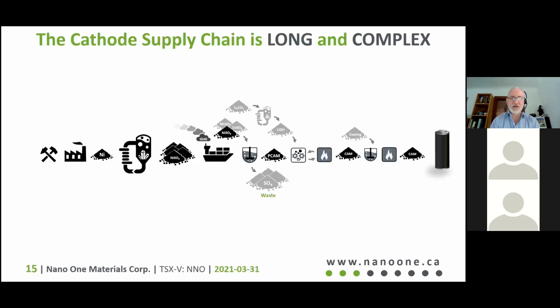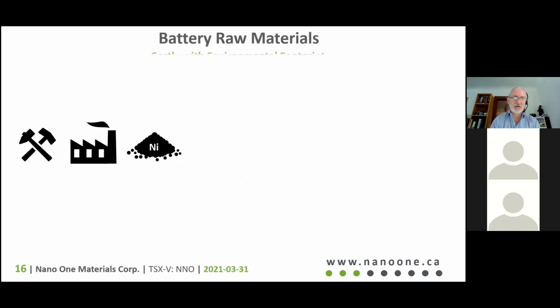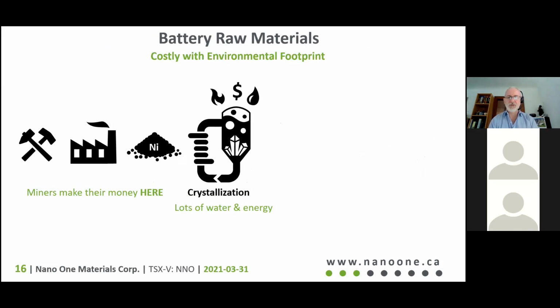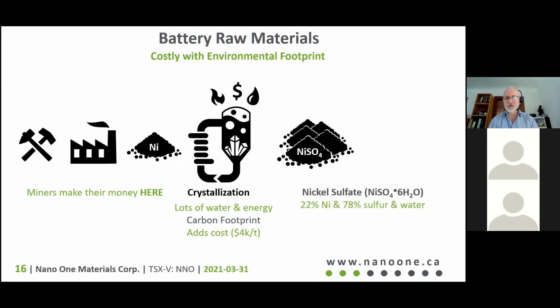The conventional supply chain is long and complicated. We'll start at the beginning with the miners and the nickel metal, or the manganese or cobalt metal. The miners make their money digging it out of the ground and producing the metal. Then if you want to make sulfate, you have to dissolve it in sulfuric acid, make the sulfate, and crystallize it to make a powder. This uses lots of water and lots of energy, and you have a huge carbon footprint because of that. It adds about $4,000 per ton to the cost of the nickel sulfate. And the nickel sulfate, when you ship it, is actually only 22% nickel. The rest is sulfur and water, because it crystallizes with 6 molecules of water for every molecule of nickel sulfate. So there's a lot of waste.